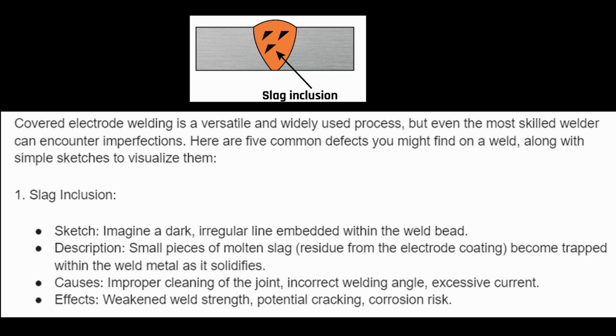Description: small pieces of molten slag, residue from the electrode coating, become trapped within the weld metal as it solidifies. Causes: improper cleaning of the joint, incorrect welding angle, excessive current. Effects: weakened weld strength, potential cracking, and there is a corrosion risk.